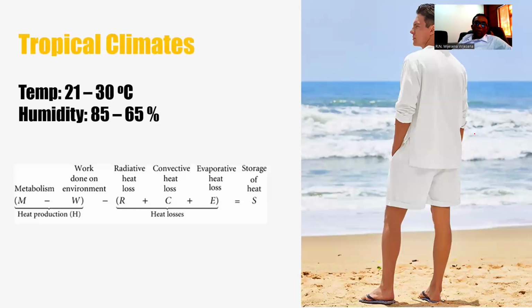Yeah. And when we have tropical climates that are characterized by average temperatures of 21 degrees to 30 degrees, we have moderate radiative, convective, and evaporative losses. And the major parameter that tends to govern, or really affect significantly, is the evaporative heat loss in these type of areas. So the textiles that we select are centered around allowing evaporative heat loss. Cottons absorb moisture, transport moisture, and spread moisture so that evaporation can take place. Of course, new materials have come in now. So we have lot of open areas. So this is the tropical climate.